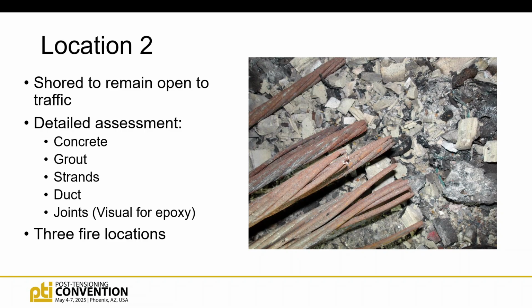And this is an interesting photo, and I hope it shows up well. Let me see if I can get the arrows to show up. There we are. So some of these strands necked down almost to a pinpoint. If you can imagine a strand under tension, it gets hot, it begins to relax, it begins to elongate, and it's going to fail plastically. But once some of these strands, roughly half of them, failed in that manner, the rest of them failed with a blunt fracture. In other words, all that force is now transferred to the remaining tendons, and they didn't have a chance to yield, they just ruptured. So we had a little bit of necking, a little bit of an early release, and then a violent rupture towards the end. And we took a bunch of samples of these to the lab to test.